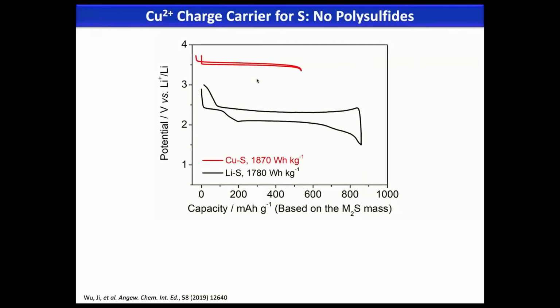So if you look at the mass including everything, including the sulfur mass and the copper ion and lithium ion charge carriers, of course, copper is too heavy. It's 63.5. Lithium is 6.94. The capacity for the entire electrode for copper is actually not that high, but because of the voltage, and this voltage gives you the quality of the capacity. The capacities are not created equal. Some capacity you have a better quality, like the copper case. In the other case, the quality is poor, right? You need more cells in series to provide the same voltage. You probably just need one cell for this copper case. And if you calculate the entire energy density from this, if we assume lithium metal as the anode, copper is actually doing better than lithium ion, all right?